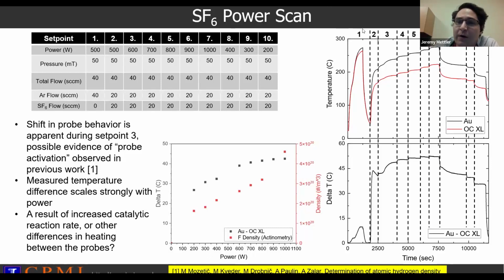The first run here, where the number 1 is just a plain argon plasma, so there shouldn't be much recombination or any reaction going on the gold surface. And then 2 through 7 are an increasing power scan. And so we see, as we introduce SF6 to the plasma, we see the temperature difference between the two probes increases as a function of the power. And the power is a good stand-in. As we raise the power, the density of the fluorine should increase as well.